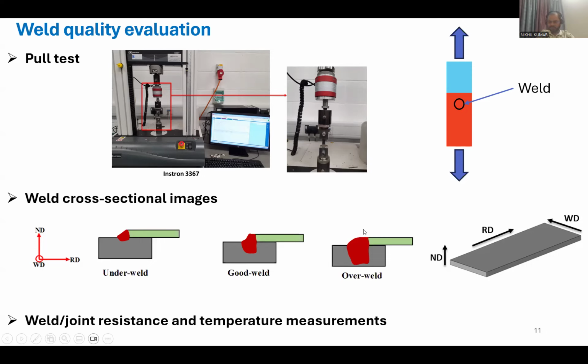And this is definitely not a good example and not a good weld because you are going to use very high energy of the laser to penetrate this bottom sheet. You will end up wasting your laser energy instead of using this as a good weld.